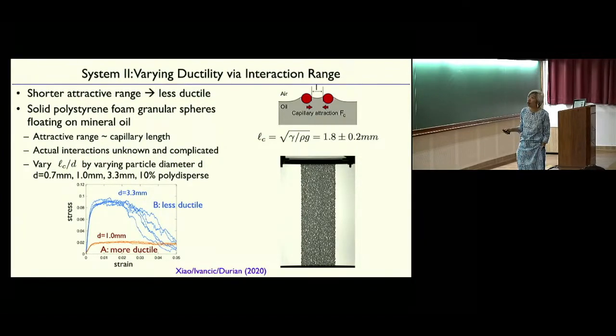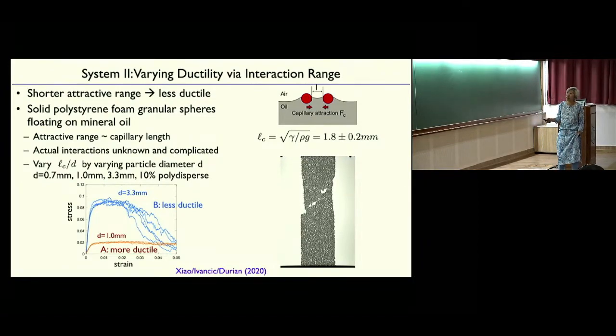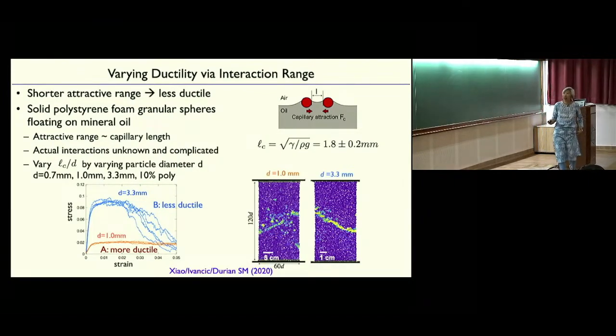I'm going to show results for 1 millimeter and 3.3 millimeter particles. The 1 millimeter particles have a stress-strain relation which is very ductile. The 3.3 millimeters are much stronger, much stiffer. But they actually show strain localization, and that's the movie. You can see the strain getting localized and then the two pulling apart. And here is another picture. For the 1 millimeter particles, the plasticity is much more distributed. For the 3.3 millimeter particles, it's highly localized in that band. So that's a different way of tuning it, by tuning the interaction range relative to the particle size.